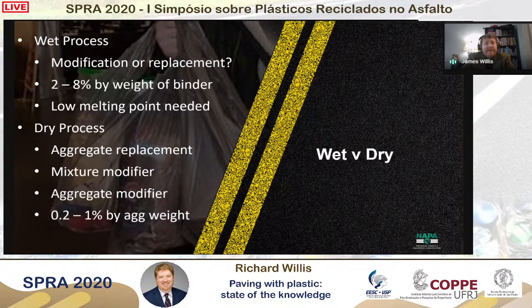On the dry process, we've seen it as an aggregate replacement, a mixture modifier, or an aggregate modifier. There are some places that say if you use the dry process, the plastic is going to melt around those aggregate particles. It's going to decrease the absorption of the aggregate and make that aggregate stronger. We're actually doing some research right now with the National Center for Asphalt Technology to evaluate those claims and see if that is really the case and it's an aggregate modifier and not as much a binder or a mixture modifier. In these instances, people are putting about 0.2 to 1% by weight of the aggregate into the mixtures, to help you understand the amount of plastic that we're using in most of these cases.